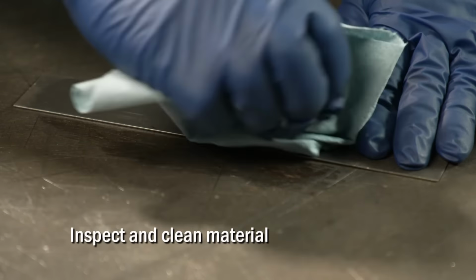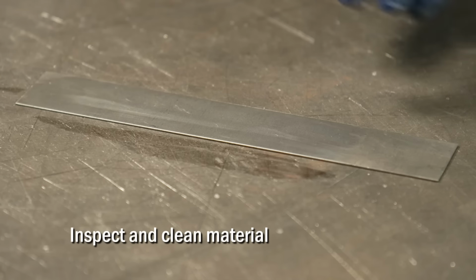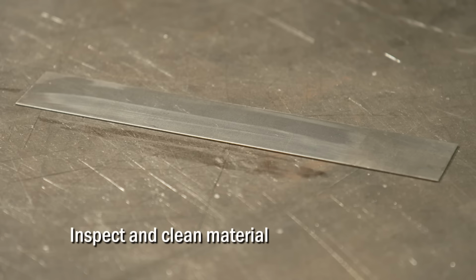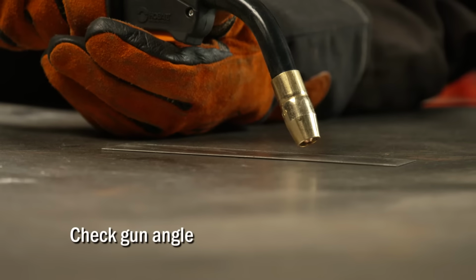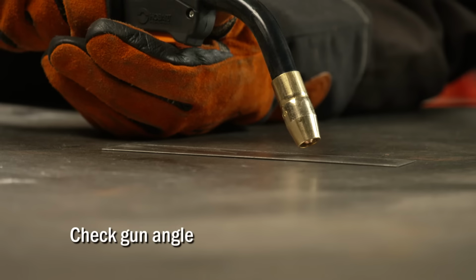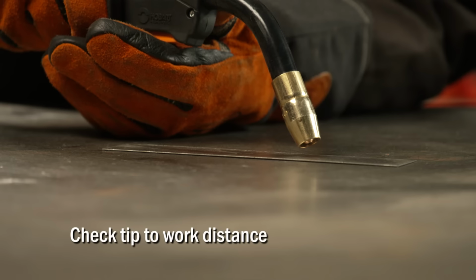Another cause of porosity is dirty base metal. Inspect and clean if necessary. Also check your gun angle. If too excessive, you will lose good gas coverage. In addition to that, check your tip to work distance. You should be around 3/8 to a ½ inch away from your material.